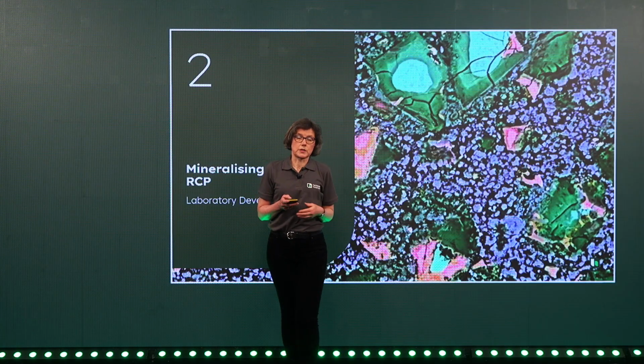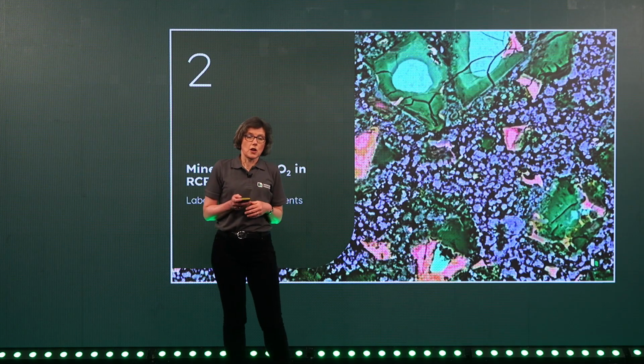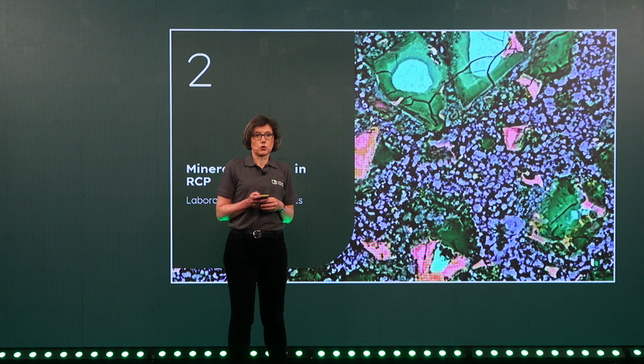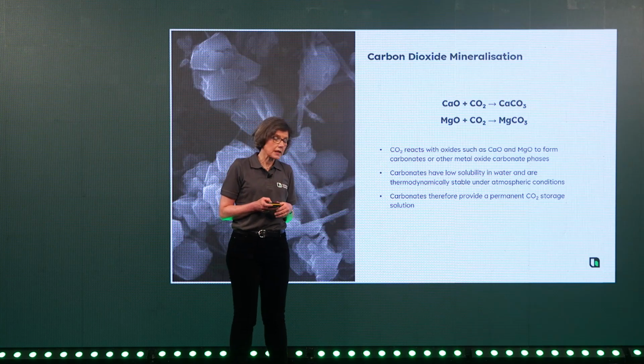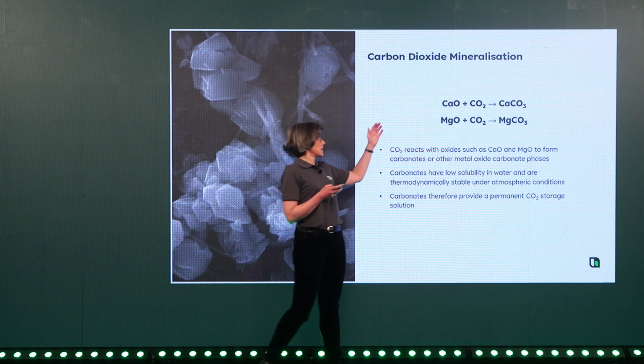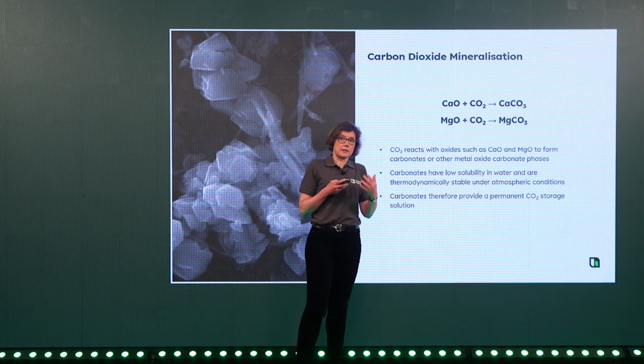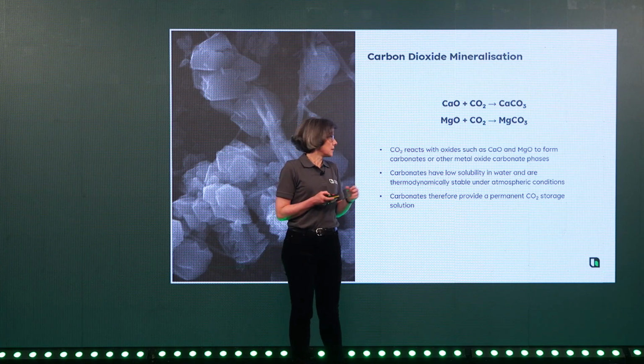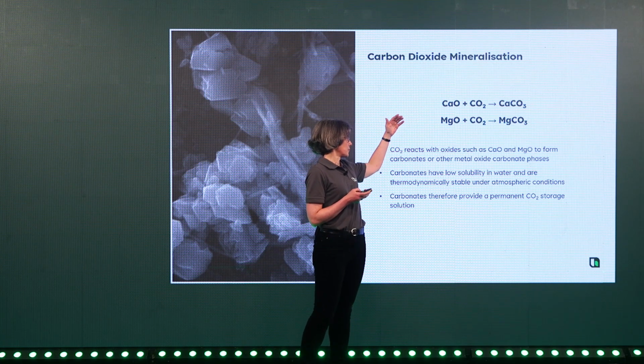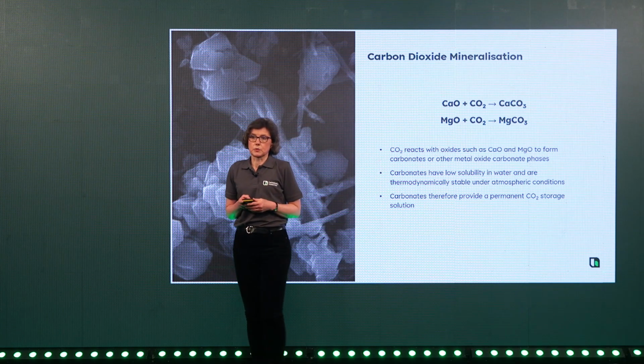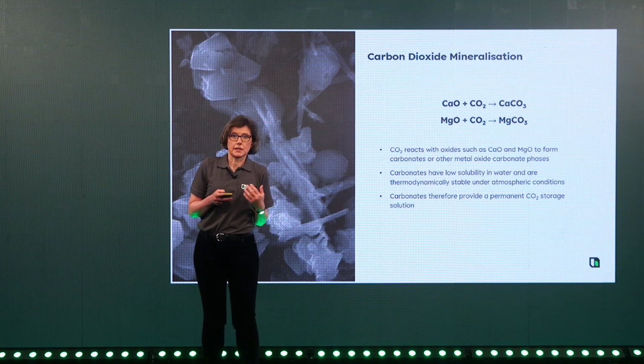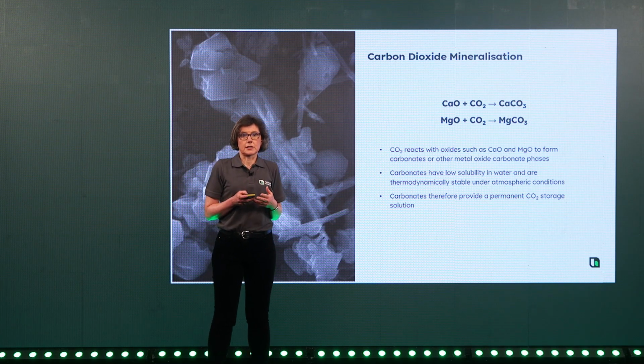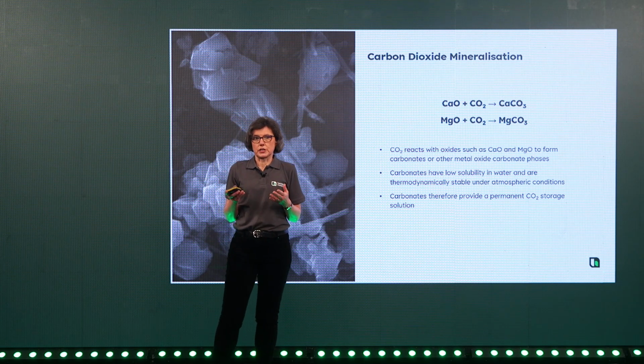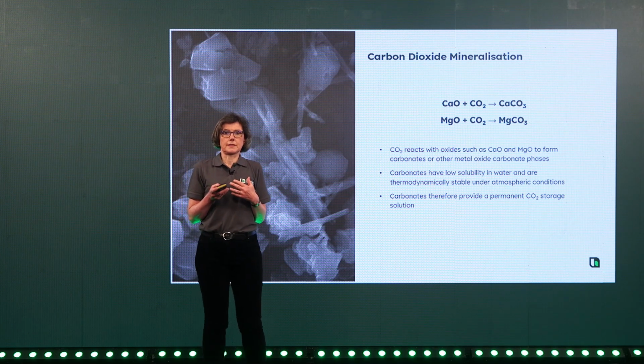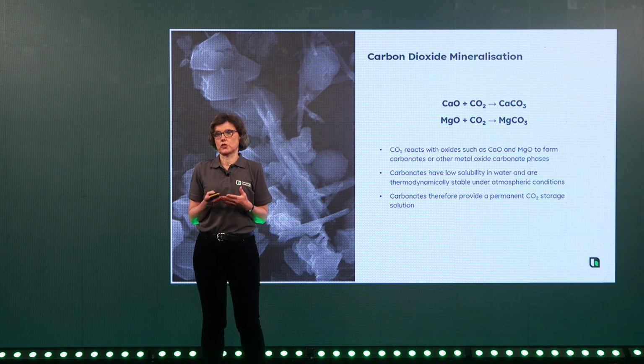That takes me now to the initial laboratory developments. What does it actually mean, mineralizing CO2 in RCP? RCP contains calcium oxide, and when it reacts with the CO2 from the emissions, from the flue gas for example, it forms calcium carbonate. Calcium carbonate is a stable oxide. It has low solubility in water, and it's thermodynamically stable under atmospheric conditions. This means that calcium carbonates actually provide permanent storage for CO2.